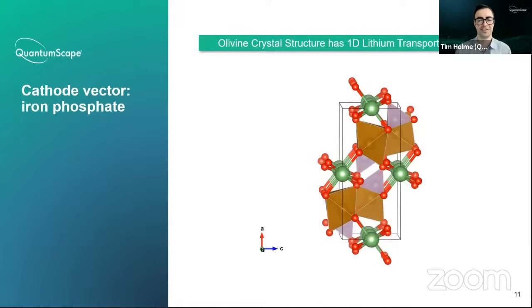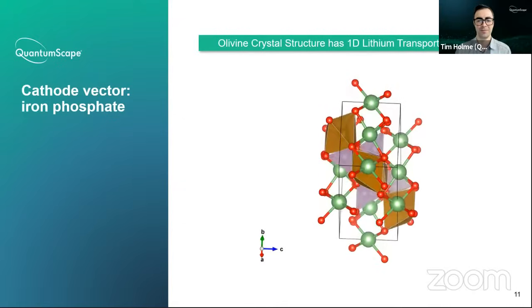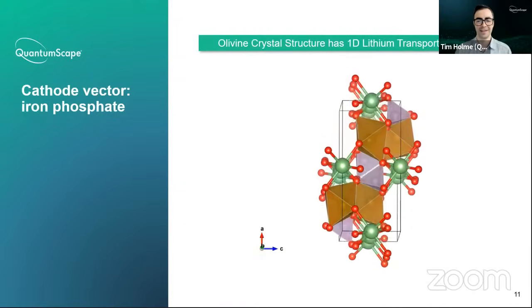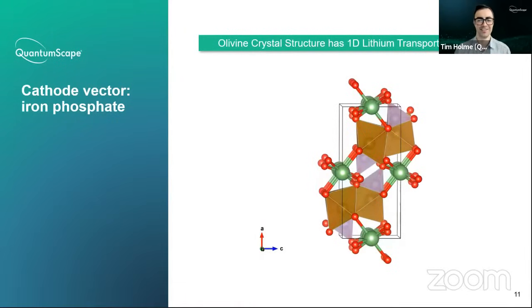So then to come back to the cathode, as Sam introduced, this is the crystal structure of lithium iron phosphate. What you can see are these ion channels, with lithium illustrated in green. As you look at this crystal structure, you can see that there are these one-dimensional pathways for lithium. Imagine driving your car on a one-lane highway and trying to get anywhere fast. You're going to go as slow as the slowest semi truck on the road. That is one of the problems in this material. In addition, the electronic conductivity in this structure is fairly low. Both of these limitations need to be addressed and have been addressed in large part by making smaller particles so that the transport pathways are shorter, coating, especially with carbon, and third, some metal doping. All three of these can improve the ion and electron transport through the structure.